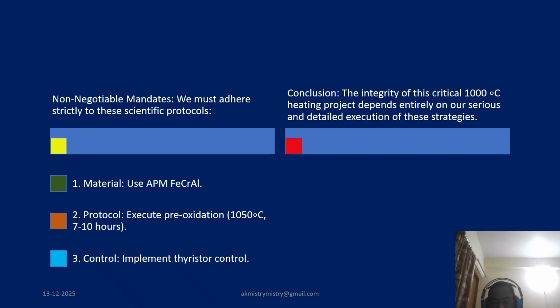So the integrity of this critical 1000 degree centigrade heating project depends entirely on our serious and detailed execution of these strategies. The difference between proper execution and failure is a factor of 2 to 4 times the expected life. We must treat the three scientific protocols as non-negotiable mandates, and what are those that we have already discussed? We have to use APM, ferrochrome aluminum material, execute pre-oxidation at 1050 for 7 to 10 hours, and implement thyristor control. Our commitment to this detail is the only way to unlock the extreme longevity required for this system.